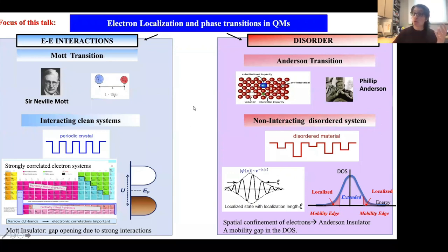Another route to drive electron localization due to correlation effects, in particular here where correlations are driven by the scattering of electrons due to disorder, is Anderson localization or Anderson transition. This is disorder-driven electron localization, which happens in systems due to imperfections present in the material. Now electrons, as shown here, are not moving in a periodic crystal, but in a random potential, and that creates sources of scattering of electrons from these impurities, which can eventually lead to spatial confinement of electrons over some region of space, as shown by this wave function envelope, indicating that electrons are mostly found in this region of space and not found in other regions. So, spatial confinement of electrons.